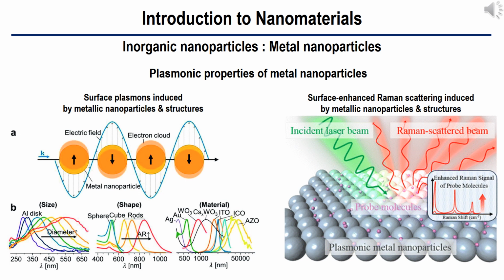When certain molecules are on the metal nanostructures, Raman scattering is greatly enhanced at the surface due to the same mechanism that excited the incident light, resulting in a greater increase in the total output. Even when an excited molecule is relatively far apart from the surface, metallic nanoparticles can induce surface plasmon phenomena. The enhancement is not equal for all frequencies, and therefore, resonance peak can work as a fingerprint to identify the molecule. The choice of surface metal is also dictated by the plasmon resonance frequency. Silver and gold are typical metals for the surface-enhanced Raman scattering because their plasmon resonance frequencies fall within these wavelength ranges, providing maximal enhancement for visible and near-infrared light.